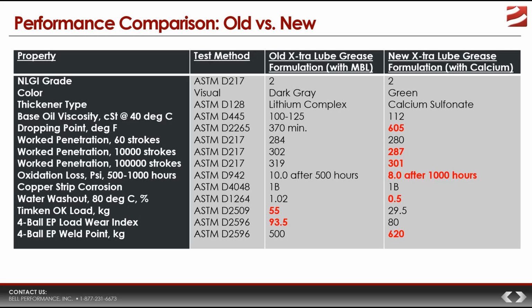You can see that both the old grease and the new grease give the same results, a 1B. That's good. The reason why copper strip corrosion testing is important is because, whether it's fuel, lubricating oil, or grease, you want it to help surfaces resist corrosion. You do not want it to be corrosive itself. And to be fair, it's kind of rare to find an oil, lubricant, or fuel that fails this copper strip corrosion test.